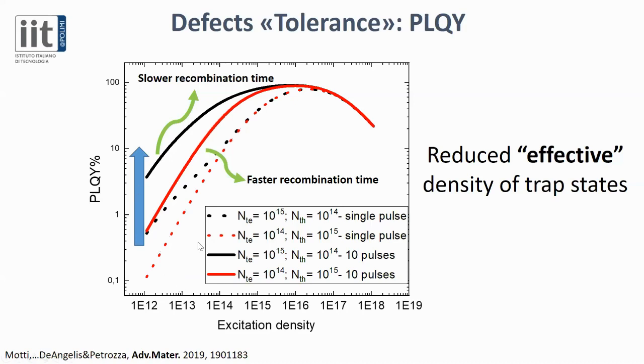So as you can see, especially at low excitation density, which is relevant for photovoltaic applications, and comparable to the density of defects you can find in three-dimensional perovskite, when we have an abundance of electron trapping states, the long lifetime of trapped carriers reduces the effective density of trap states. In fact, once you trap an electron, it lives so long that it is somehow self-healing that defect. So if another photon comes, it finds that state already occupied, so the electron doesn't get trapped again. This is a sort of self-healing of the material itself.